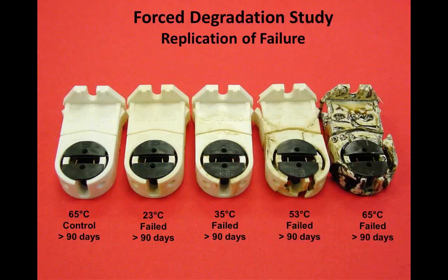And you look at these different tombstones going from left to right, showing a control sample that was just in a sealed container with no exposure to dicyclohexylamine. And again, marching from left to right, you see a dramatic impact that DCH has on polycarbonate when it's exposed. So this was really proof positive that exposure of the polycarbonate to DCH is causing this issue.